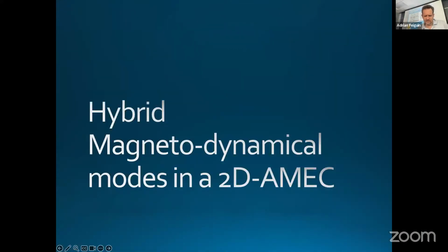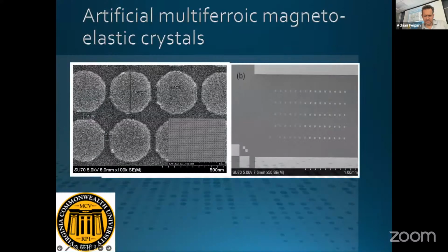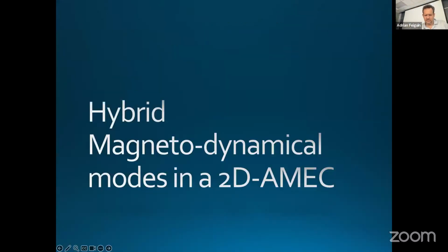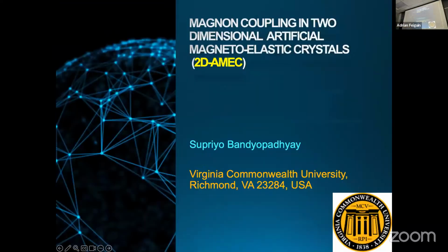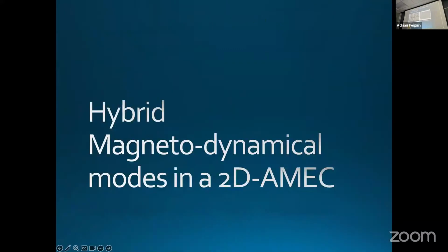So what's the thickness for those? Okay, the thickness for these nanomagnets is between 2 and 15 nanometers. Typically, we use 6 nanometers. How did you make them? With electron beam lithography. We pattern the substrate with electron beam lithography, and then we evaporate cobalt, followed by liftoff. Okay, it goes back, works.